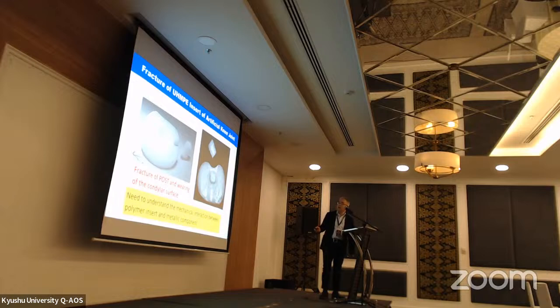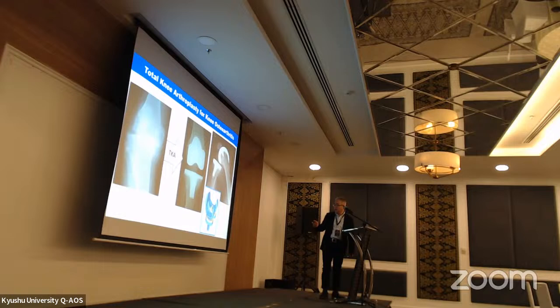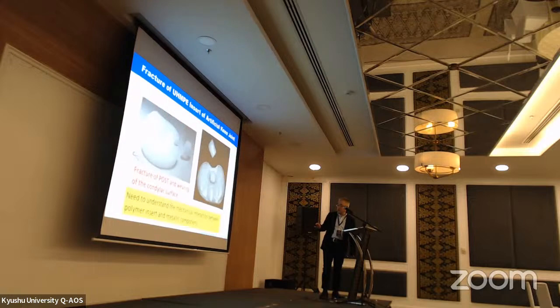One problem is fracture of the post. This is ultra high molecular weight polyethylene, a polymer, so there is contact between the polymer and the metal. This blue one is the metallic part, and this white one is the polymer. The polymer post is in contact with the metallic part, so the polymer faces a very severe situation in bending motion.